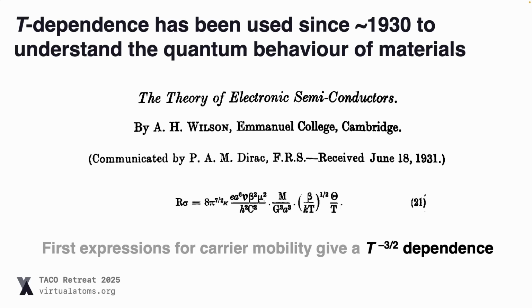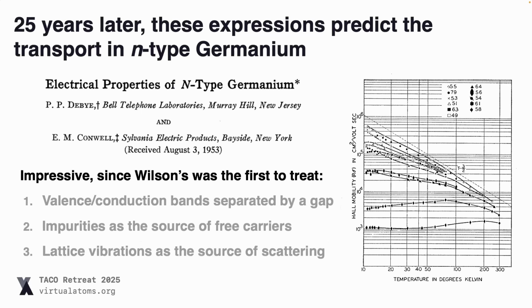So going back to this seminal work by A.H. Wilson in 1931, where he derived an expression for carrier mobility given the assumption that electrons are scattered by lattice vibrations. And what he found was that under this assumption, you would expect your mobility to have this T to the minus 3/2 temperature dependence. So it decays with this kind of power law. And what was very nice was that 25 years later, when we finally were able to grow high quality single crystals of germanium, some of the crystals showed very nice agreement to the mobility trend that he predicted. And so I think this is very nice.